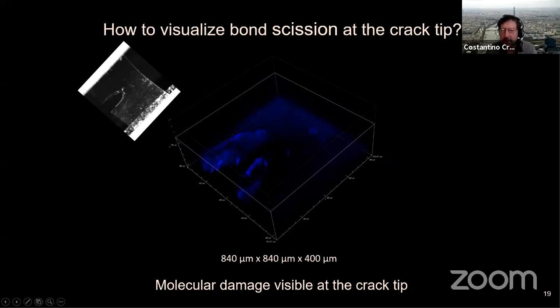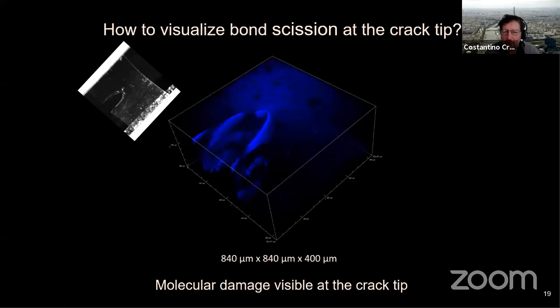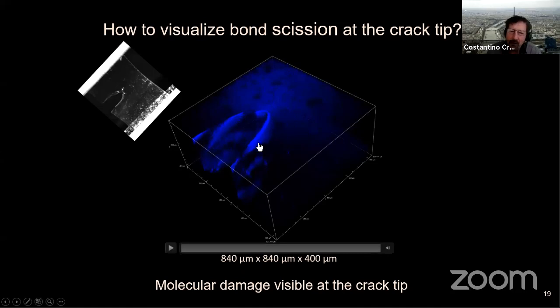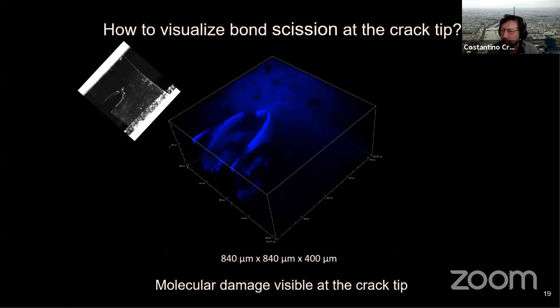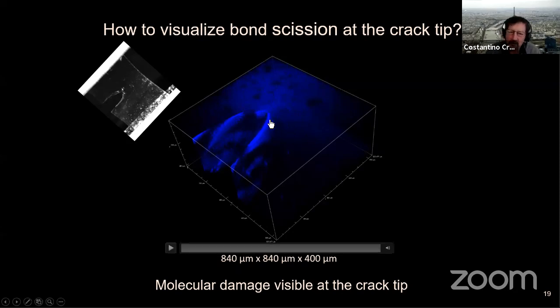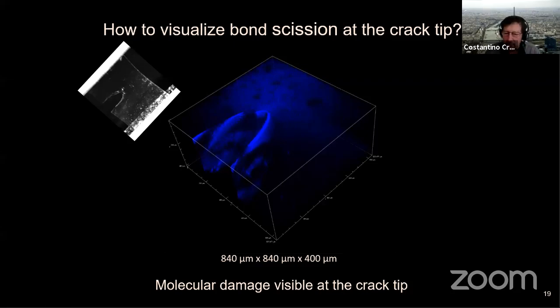And if you look at the picture here, it gives you some signal. But now in this case, the amplitude has been boosted. But you can see some detection even in this kind of material. Not easy, again, to quantify because you have background. A lot of this is just background noise. So you have an issue of separating the signal from the background. But it looks like you have some detection here of activation of the molecule. And so some molecular damage is visible.